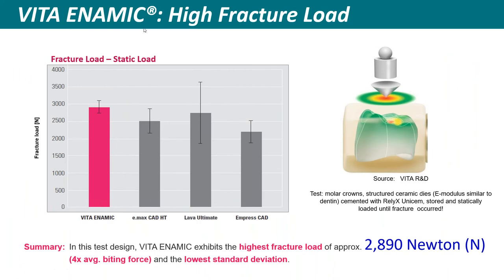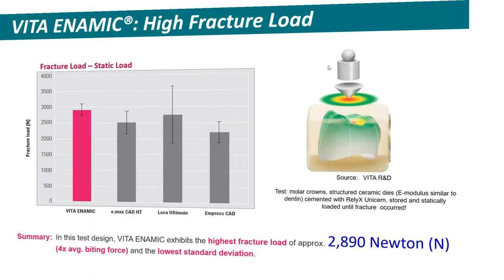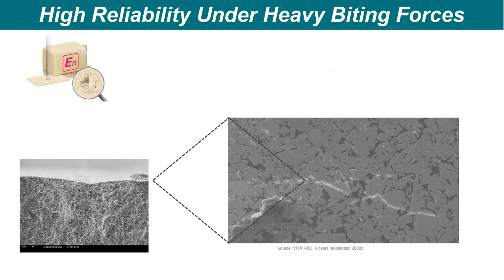Again, what we're concerned about, what VITA makes sure of, is that once it's milled out to a restoration, the fracture load of the restoration design is as high as it can get. So you can see here, enamic is very high. These are Newtons here, right? And Mark was talking about 1,000 as being severe for a bruxer once you get into parafunctional habits. 1,000 Newtons is a critical point. Bruxers are around 2,000. So you can see here that this enamic material is close to 3,000 Newtons. So it satisfies the requirement of a very heavy biting patient, especially when it comes to implants. So you can be well aware of that as far as aesthetics, but also the strength of it is adequate to do this.